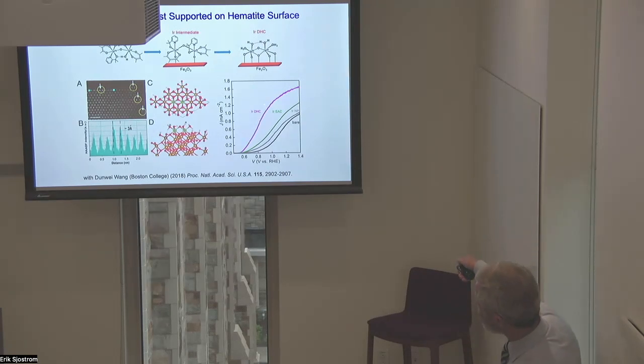And what you can see is that this dual heterogenized catalyst, or DHC, improves the photocurrent as a function of potential dramatically compared to bare hematite or iridium nanoparticles or single iridium atoms, despite the fact that, as I mentioned, iridium oxide nanoparticles are the best known heterogeneous catalyst that has been found. So this is significantly better. And it can do a lot of chemistry besides this.